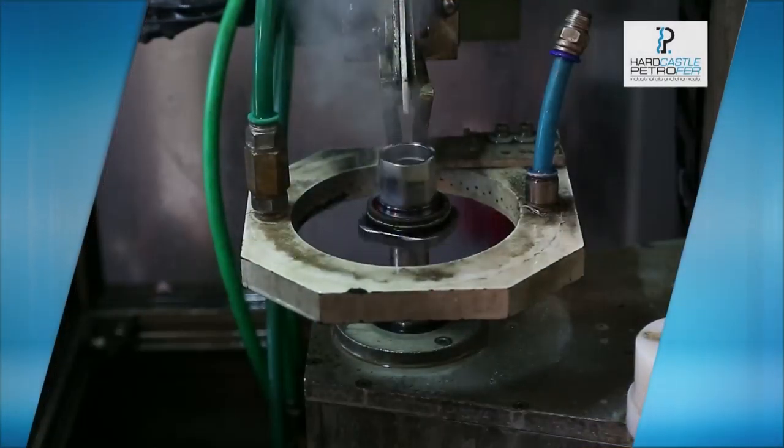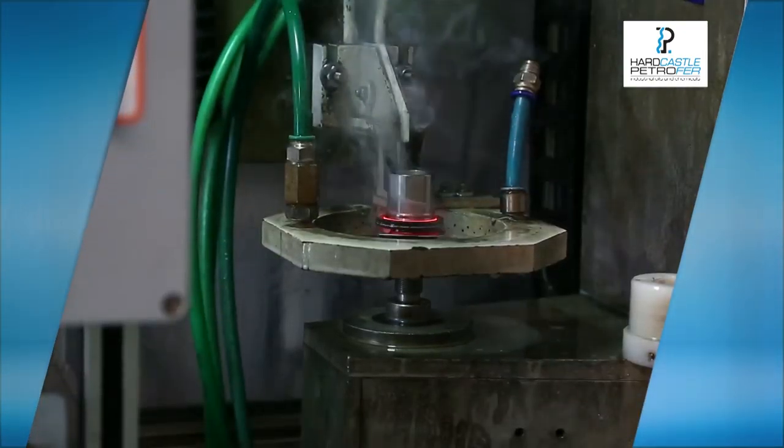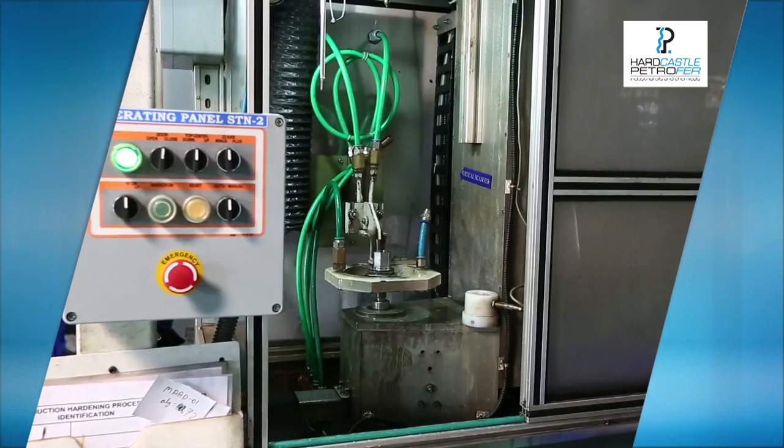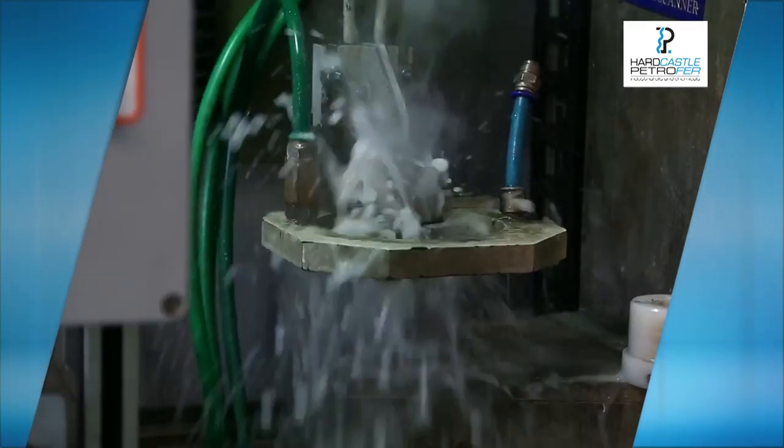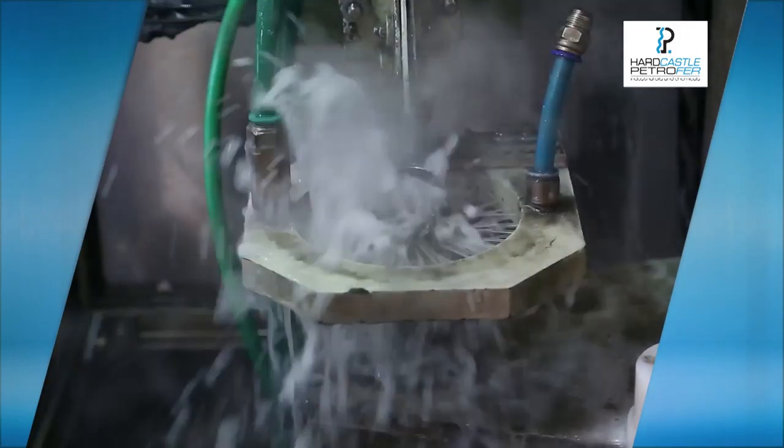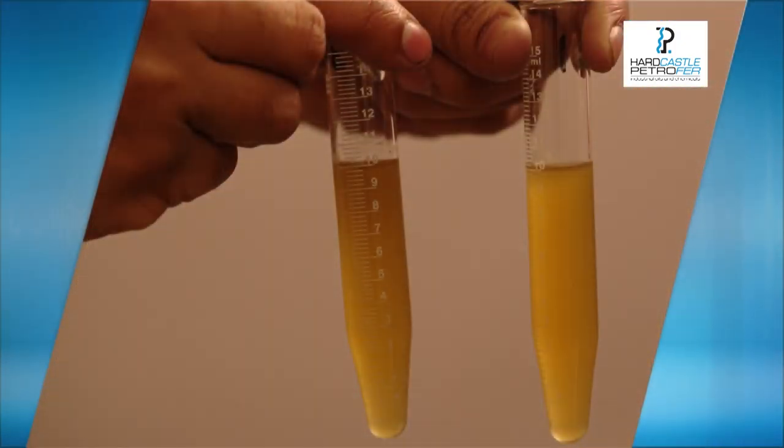The life of water miscible quenchants is usually limited by several factors. In the case of induction hardening operations, the solution has to be replaced after periodic intervals due to the effects of contaminations from previous processes. The thermal loading can also take its toll in the long term. In view of this and the need to control the concentration of solution, monitoring is required for polymer quenchant solutions.